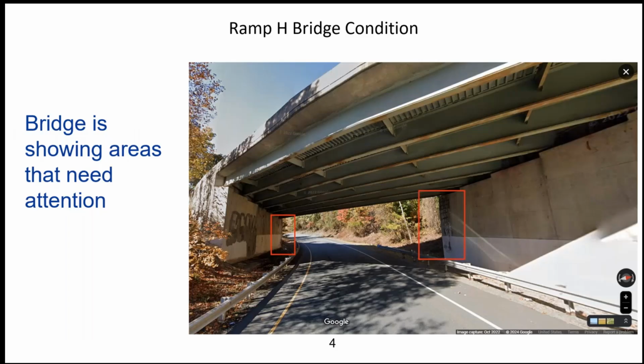So as you approach the bridge, you could look at the abutments, as circled in the red square, the areas of the repair, one on the left and one on the right. These are symptoms of leaky joints, where the icing salts cause corrosion and spalling of the concrete. And this is exactly what happened in this case.